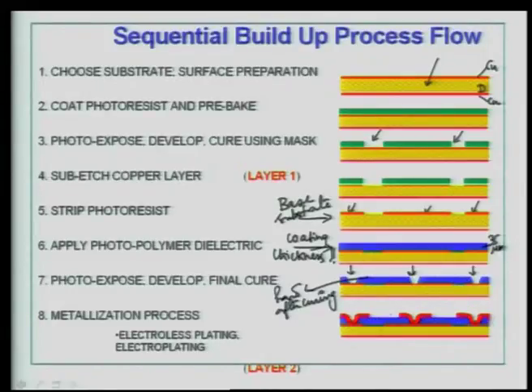Now, you have to metallize this microvia. So, you can see that the hole walls are not conductive. So, you do an electroless process, then followed by electroplating process, and then you can see all of these layers have been coated with copper. You can see electroless first, followed by a flash electroplating to metallize the hole wall, and in addition you can see the hole wall copper at the bottom touches the copper plane in the adjacent layer. So, this is how a connection has been established between this layer and this layer,